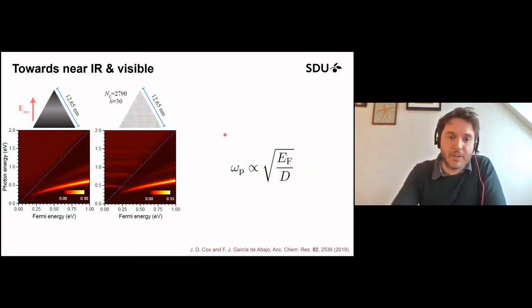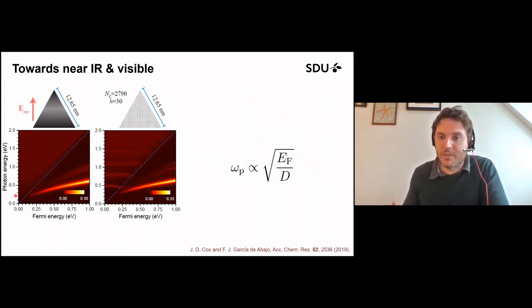One area I've been looking at quite a lot, coming back to graphene nanostructures, is how to tune the plasmon resonances so that they can be used in the visible regime. You might have noticed in some of the earlier slides that the energies of these plasmons are characteristically low in graphene. They're in the infrared regime. And in noble metal particles, you have them in the visible regime. This can be a technological disadvantage depending on your application. But one simple way to boost the plasmon resonances to higher energies is to make your graphene nano islands smaller and smaller. And just the confinement alone can push up that energy. And then you can also increase the Fermi energy in graphene to further enhance the energy of the plasmon.